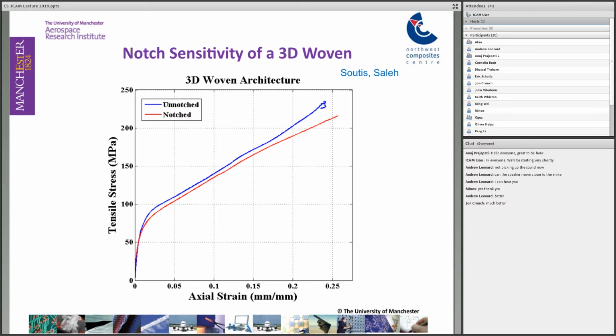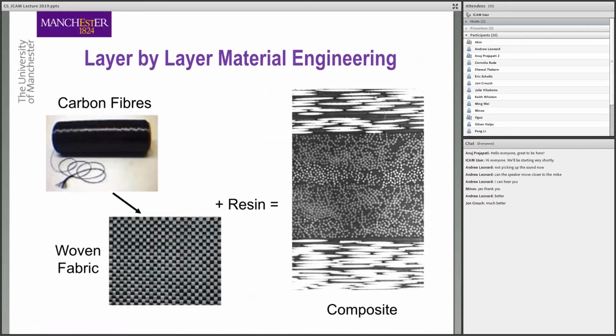So we spoke about this layer by layer material engineering, where we have the carbon fibers or the woven fabrics mixed with resin, and we try to find ways of making our composite construction more damage resistant, more damage tolerant. And the final way of doing that, since we come from Manchester, we're going to introduce a magic ingredient in the form of graphene. So instead of using the 3D fiber architecture or the hybridization, we try to modify the resin and make the resin tougher with graphene particles.